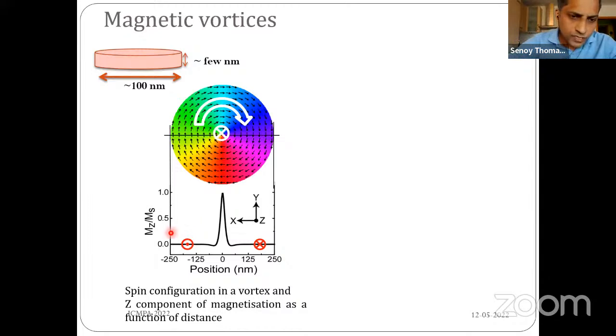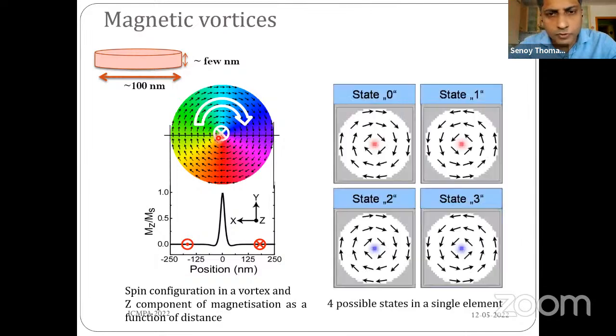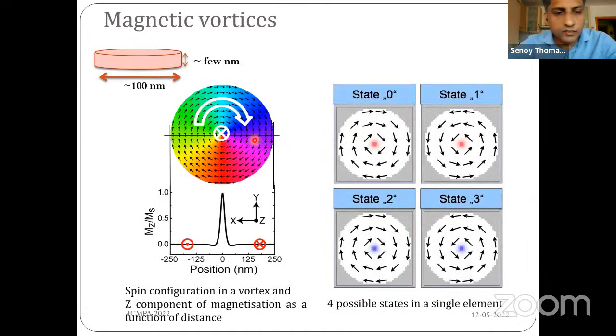Now if you measure the Z component of magnetization as a function of position, one can see large values of the Z component of magnetization due to the core of the magnetic vortex. Depending upon the sign of polarity and chirality, four different states are possible in a single element. This is very important as far as high-density storage is concerned. Now the question is how one will realize vortex structures in nanostructures.